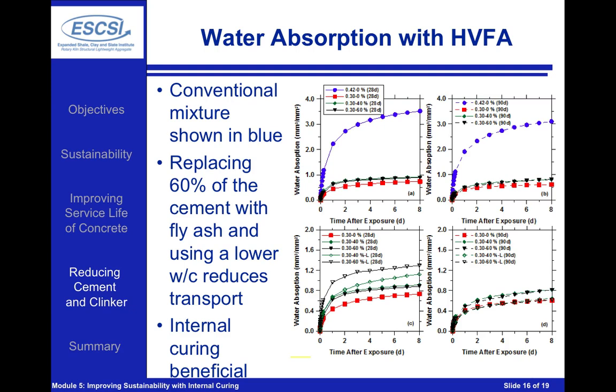We see in all of those cases, whether it's a straight cement system or whether 40 or 60% of the cement has been replaced, the water absorption is substantially lower than what we saw in our reference conventional bridge deck concrete mixture. This really talks to the benefits of internal curing. In addition, these internally cured mixtures had the same cracking potential that we saw in the conventional 0.42 water to cement ratio mixture. So this is really a big benefit. By using a lower water to cement ratio, we're able to overcome some of the early strength limitations. We're able to improve our transport properties, and we're able to reduce the risk of cracking in those mixtures.